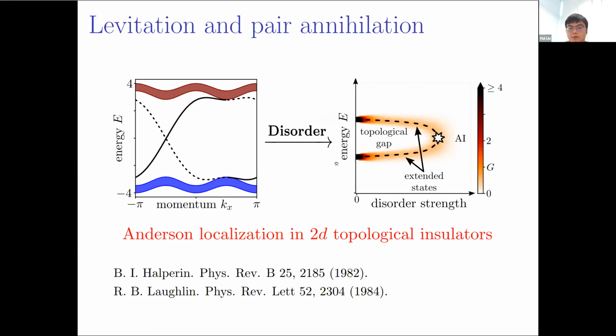Now, when the disorder strength is increased, these two extended states carrying opposite topological invariance move towards each other in energy. In this process, the topological gap would become smaller and smaller and disappeared when these two extended states meet and annihilate at zero energy. After that, this system would become topologically trivial Anderson insulators. This is how Anderson localization happens in two-dimensional topological insulators.